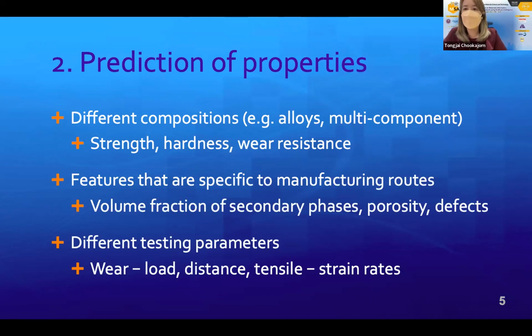The second example is prediction of properties using something that is specific to the manufacturing route and that makes it difficult to find information or data in the current literature. Those would be volume fraction of secondary phases, porosity, and defects, depending on the process. And lastly, we can have different testing parameters that could affect the values or the magnitude of your properties. For example, during a wear test, you can have different volume loss at different loads and distance. And sometimes data on this kind of properties cannot be found in the literature.